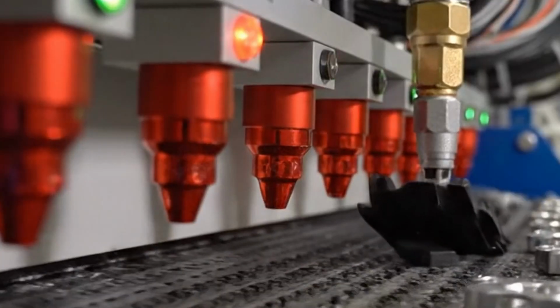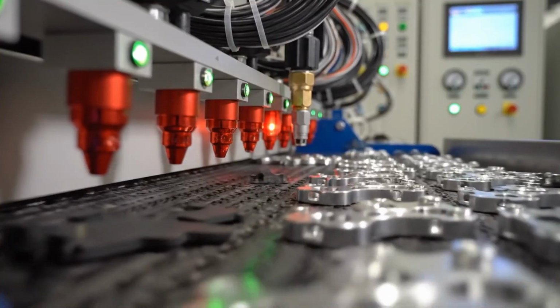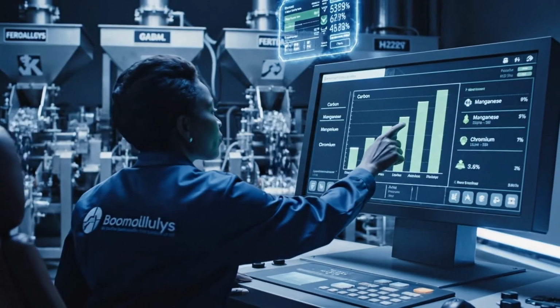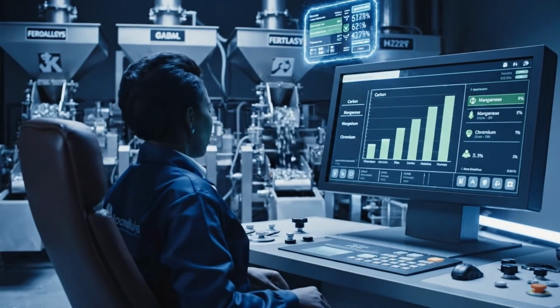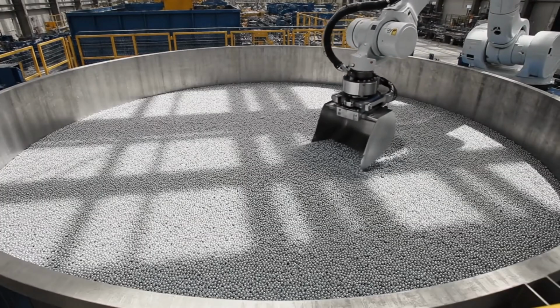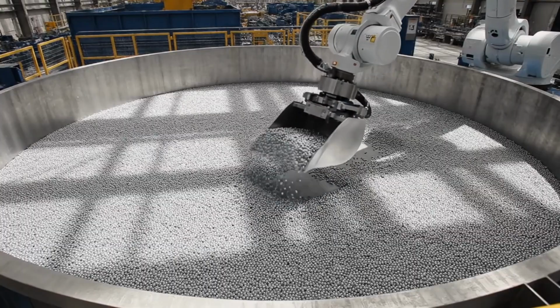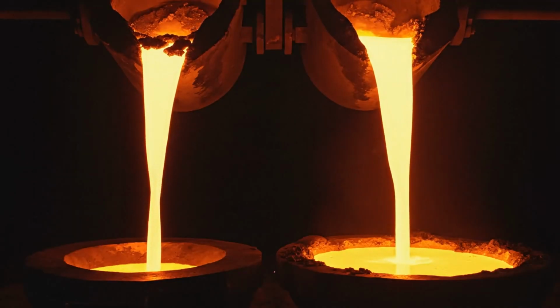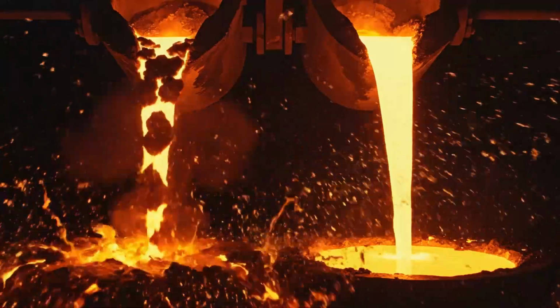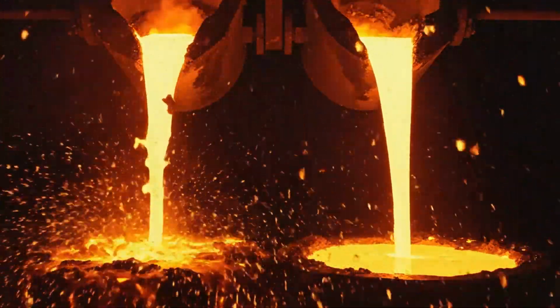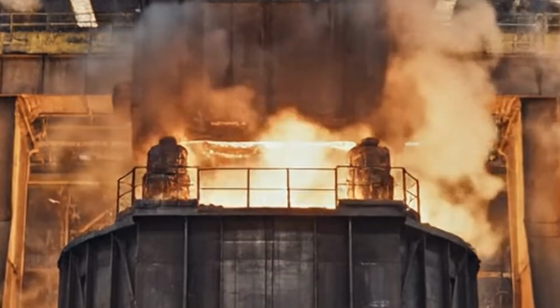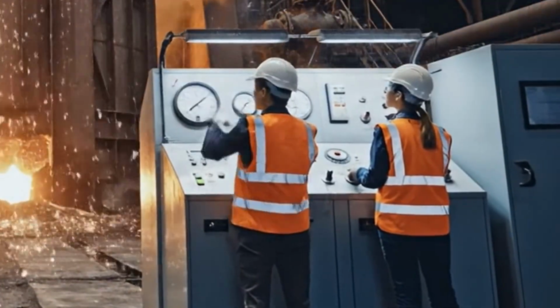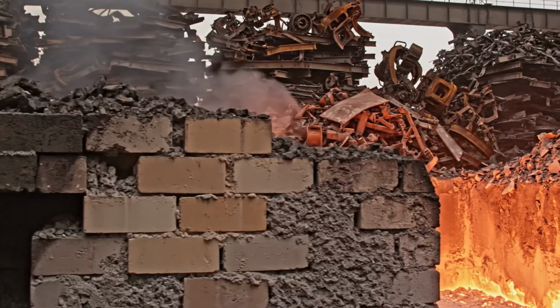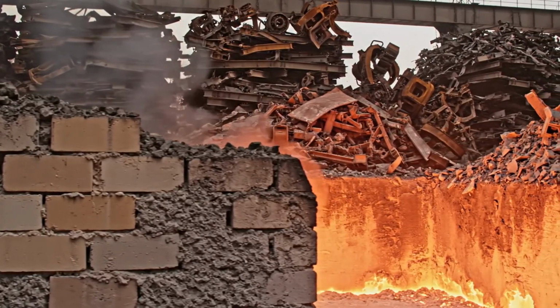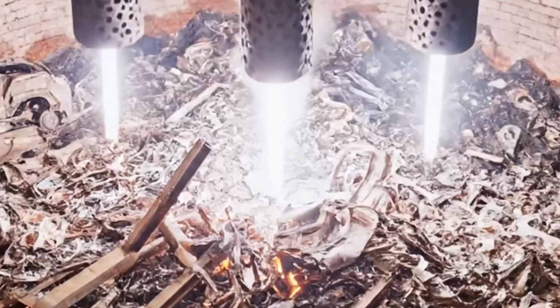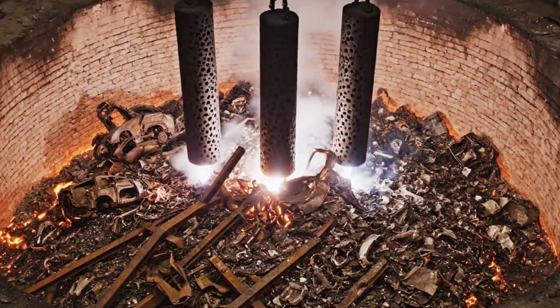With the scrap metal prepared, one of the most spectacular moments in the entire factory arrives: melting in an electric arc furnace. The material enters an enormous chamber lined with refractory materials capable of withstanding extreme heat. When the furnace closes, 3 gigantic graphite electrodes descend onto the charge. An intense electric arc is generated between them and the metal, a discharge of energy capable of raising the temperature to brutal levels and rapidly melting the steel scrap. Inside the furnace, the steel begins to collapse in on itself. The solid pieces lose their shape, soften, and eventually become an incandescent liquid mass.